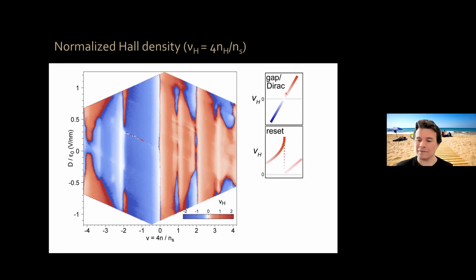Now, you can also have these resets, where your normalized Hall density grows and then experiences a drop close to 0 and then continues growing without changing sign. These resets correspond to those cascades of phase transitions that I mentioned earlier in magic angle bilayer graphene. You can see this behavior can be in red or in blue. For example, let me show you one in blue here. You have lighter blue, which becomes darker blue, which then goes to white, close to 0, which then becomes lighter blue and then darker blue. So that corresponds to a reset type of behavior. You can see similar resets also here and in other places.